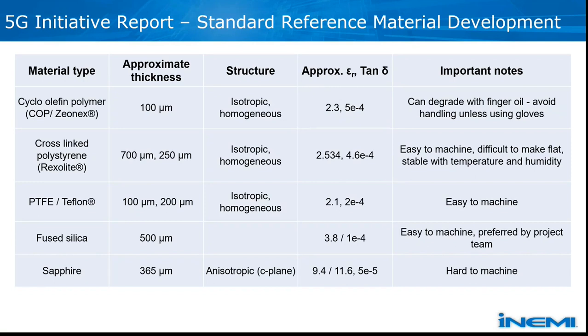So what we did within task one, we listed some candidates for the standard reference materials. You can see them on the slide. Those are the COP material, Rexolite, PTFE, fused silica, and sapphire. We evaluated the basic parameters of those materials, like approximate thickness, which is available, whether those materials are isotropic or anisotropic. Most of them are said to be isotropic. Only the sapphire from the candidates is an anisotropic material.